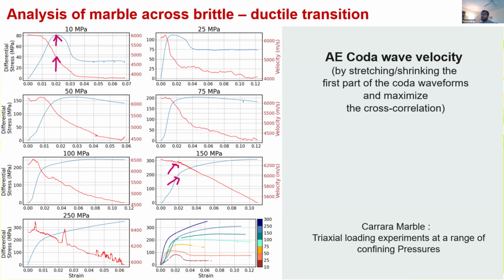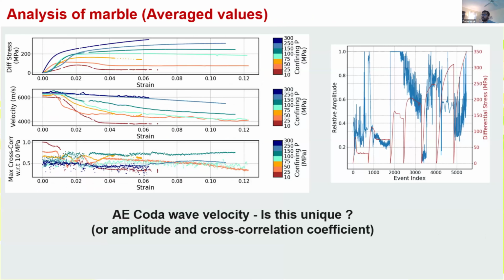Okay. So the common features to look at are velocity. Then the other things that people also look at are the cross correlation coefficient, as well as the amplitude, right? So on the figure on the left, I'm showing all the experiments together. At the top is the differential stress for the different experiments as you go from brittle to ductile, and then the change in velocity, as well as the change in the peak of the cross-correlation coefficient. In all of these cases for cross-correlation, I'm going to reference it to the undamaged 10 MPa sample. Again, I'm not doing cross-correlation with respect to its own experiment because we want to compare with respect to each other and across the different experiments.